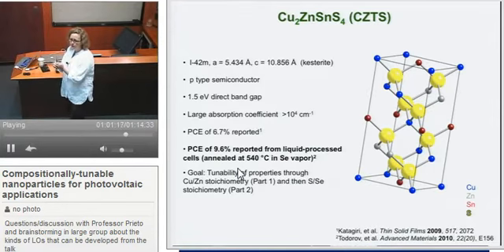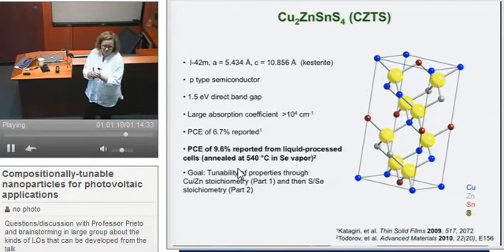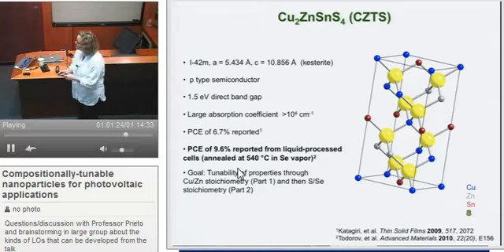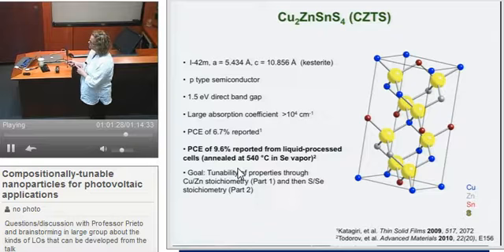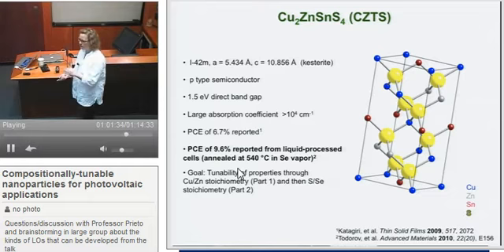So instead of all these interfaces between nanoparticles where you can get recombination, you have these micron-sized crystals and much better electrical conductivity. However, there are several theory papers that say that when you put selenium in on the sulfur site, so replace all these yellow spheres with selenium, the band gap should drop to 1 eV. And it seems like that's not ideal for photovoltaics.